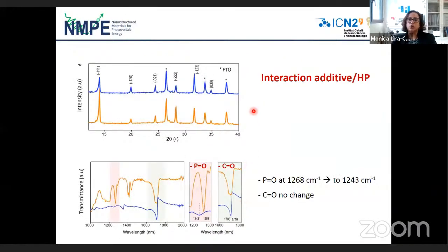One more nice thing is the interaction between the additive and the halide perovskite. One very nice result was observed by FTIR. You can see that the peak of the absorption band that corresponds to the phosphonate at 1268 was observed to shift to 1243. If we analyze the peak for the carboxylate, we observe no change at all. This is very interesting because it's telling us that it's the phosphonate that is the most important, or has the most interesting interaction with the halide perovskite.